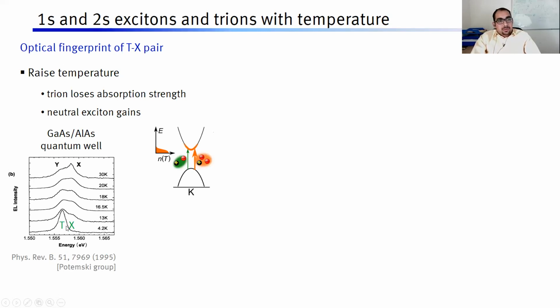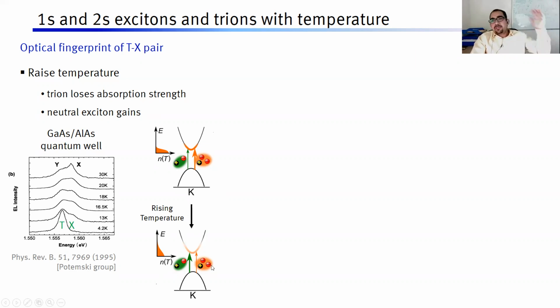So the strength of this exciton will be very low if you have a filled conduction band in some sense, right? So this is why at low temperatures, when the excess carriers are frozen in the center of the conduction band, you have lots of trions, but fewer excitons. However, when you raise the temperature, you have a Fermi-Dirac redistribution of these carriers, and this spreads the electrons to higher energies. And then you have empty states available for the creation of excitons, but the trions reduce now because you have fewer electrons. So you should have an exciton which is gaining strength, whereas a trion going down in strength. This process is also called transfer of oscillator strength, because you have transferred the strength from one species to the other.